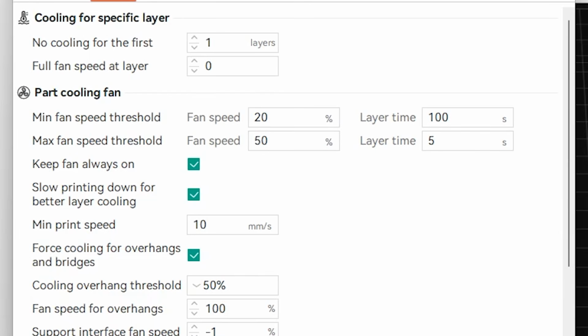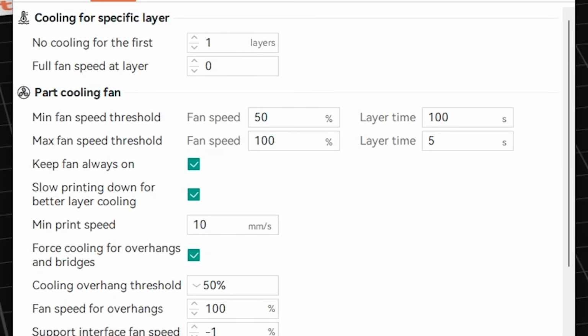But you are still cooling sections that are either very small and need that extra cooling, or extreme overhangs, or bridging. For my 200 Celsius profile, I found that 50% fan speed was good enough for all my bridging, extreme overhang needs. So I set the rest of the part to be cooled at 20% fan speed. And I printed out a Benchy with those settings. For my 230 Celsius profile, I found that I needed 50% fan speed for my normal part, so the bigger pieces, and then I needed 100% part cooling for overhangs, bridging, and small sections. I again printed out another Benchy, and this is what it looks like.